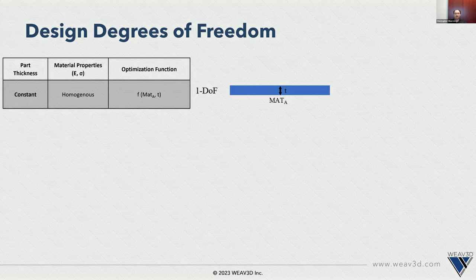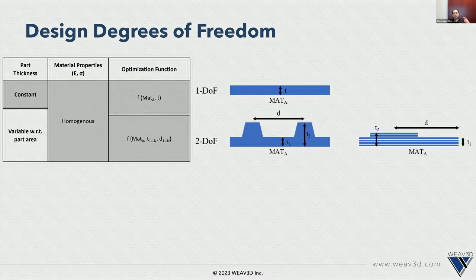So kind of the simplest possible version of this is something like sheet metal, where the part curvature and things like that may be defined by the application, but by changing the gauge of the sheet metal, so the thickness of the sheet metal, you effectively change the stiffness and load capacity of that material, even though its strength remains the same and its modulus remains the same. So when we talk about a single degree of freedom, what I'm generally referring to is you have a homogeneous material over the entire surface of the structure, and you are just changing thickness. We then can talk about 2 degrees of freedom.